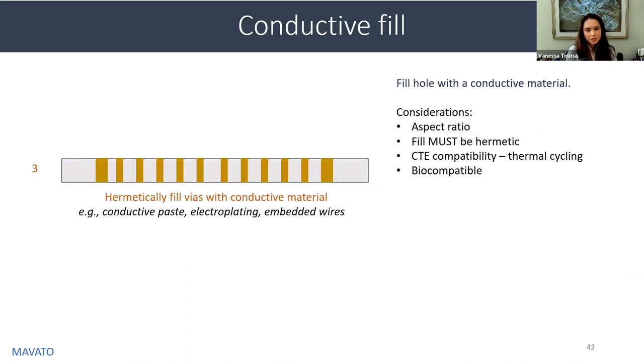Now you need to fill the holes with a conductor. Importantly, they need to be filled such that the substrate is hermetic. No gaps, no voids, no cracks. And all the materials you're choosing have to be non-toxic. So you can't just use copper, which is a commonly used fill for this, without a lot of extra work that you'd have to do. I'll dive into this step a little bit deeper in a couple of slides, but let's just move on to the last step for now.